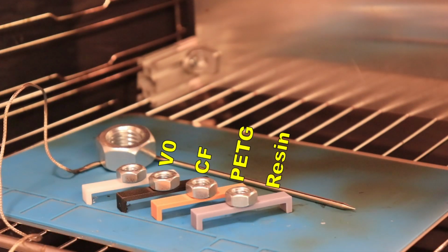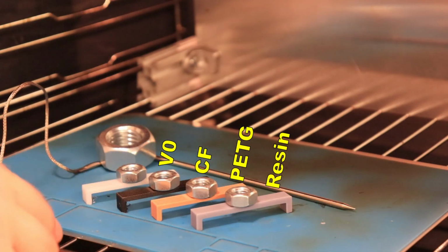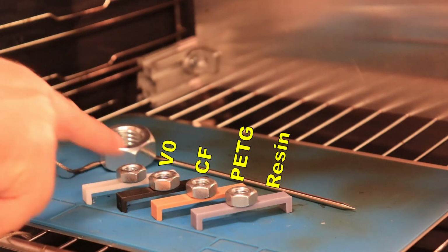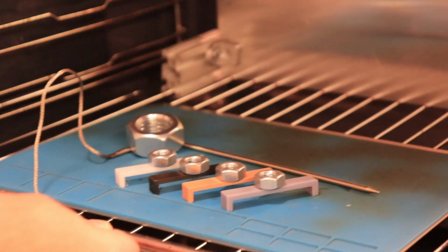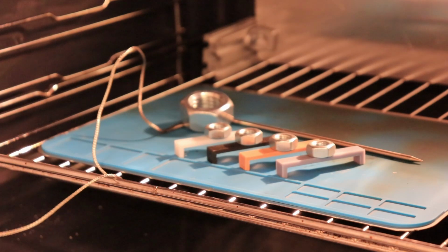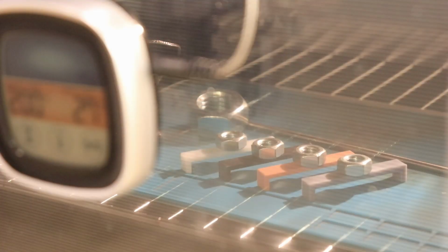Another temperature test in the oven, and I also have some resin test objects too, because I have several experiments in progress. And I want to record the temperature of the first deformation. And I will follow the temperature with this cooking thermometer. And this part is speeded up 25 times. And all three PETGs started to deform at approximately 65-66 degrees Celsius.